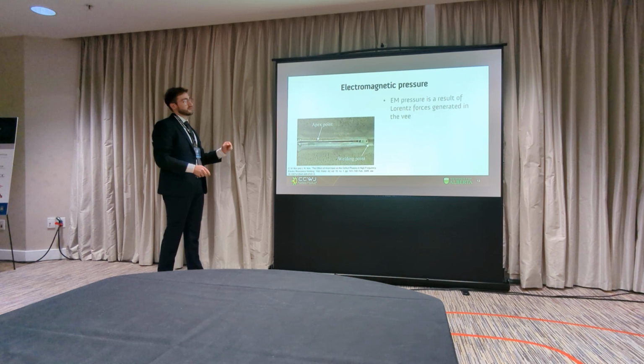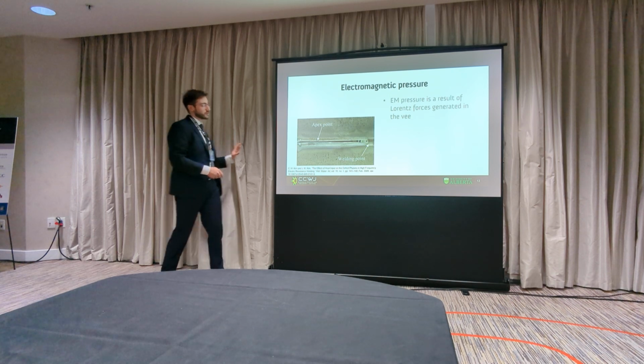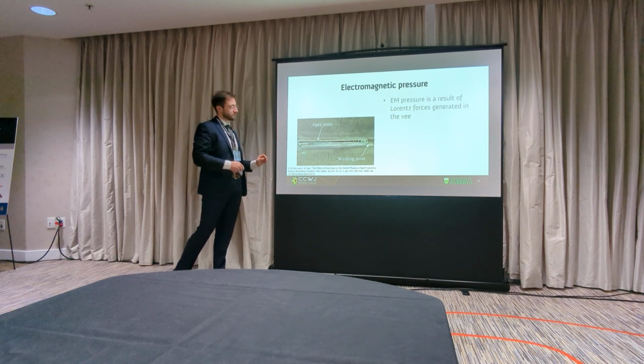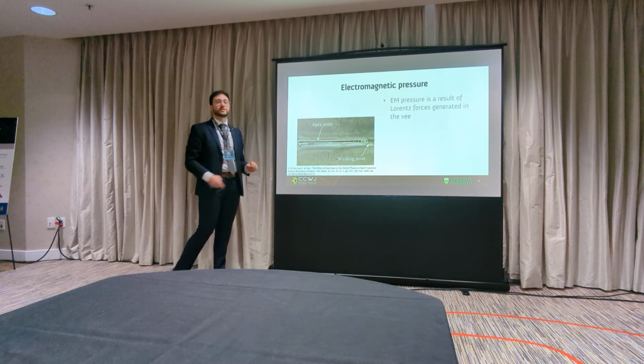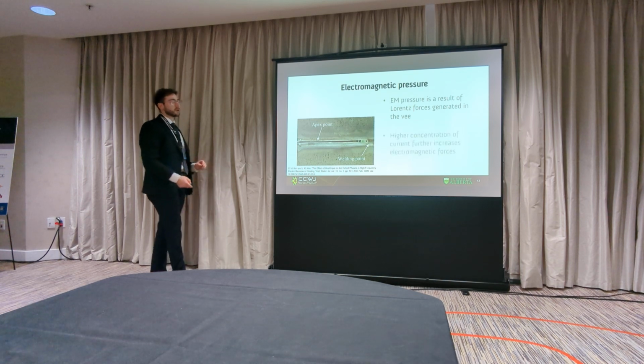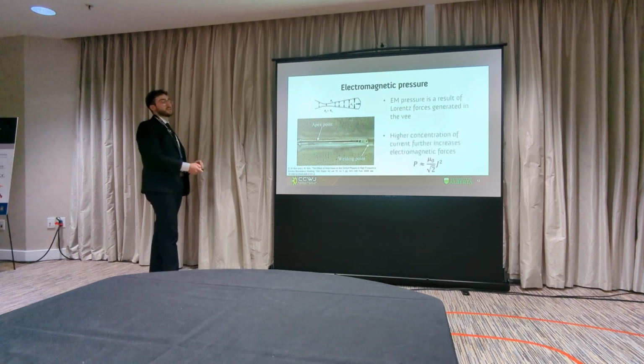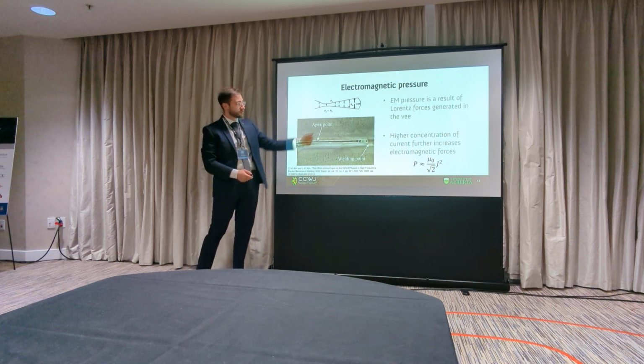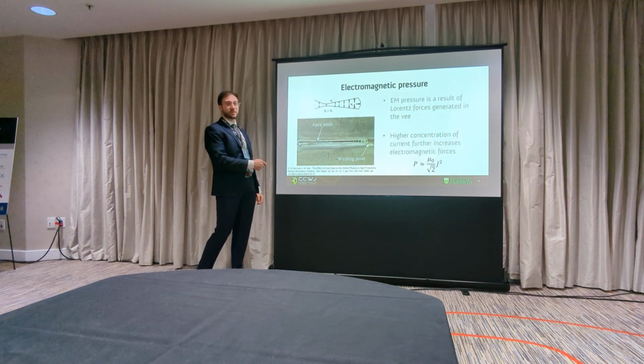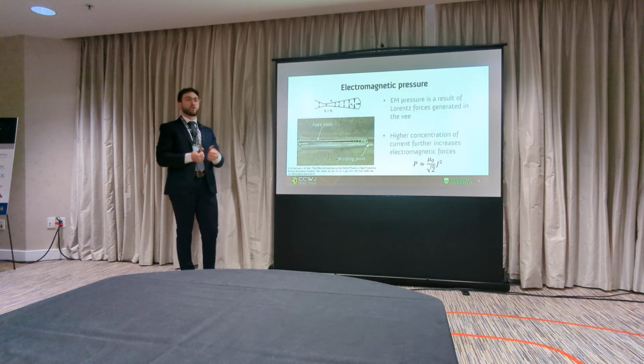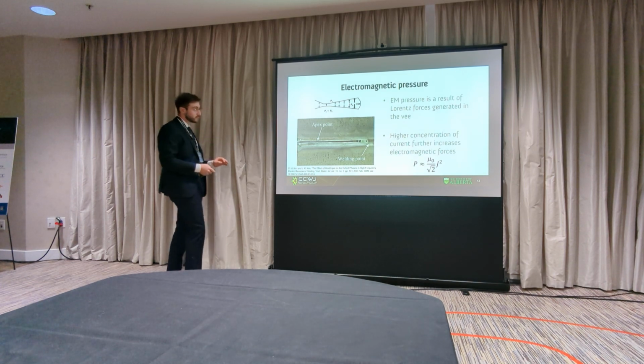But you can see that these points aren't shared. They're not the same space. And the reason why is because of these forces. So as you go towards the weld point, and the current would follow this path here, your current density is going to increase. And current density is directly indicative of these Lorentz forces, which act actually normal to these weld interfaces. And so they actually cause the expulsion or the opening of the V. So that's a key aspect here.